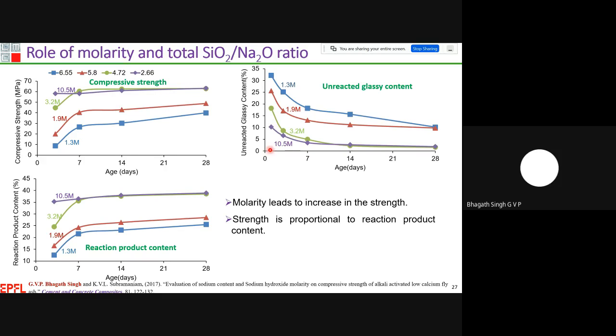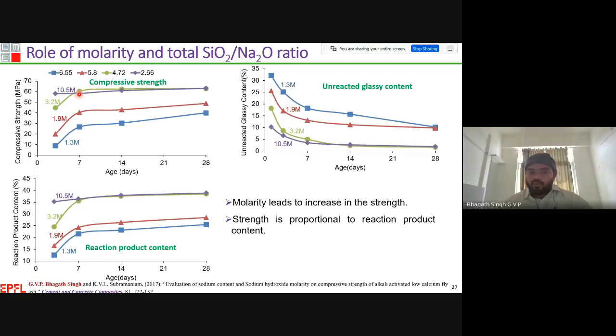Due to this reason, after 7 days, you can see the compressive strength is more or less the same. Why? Because the glass is already dissolved by 7 days, and both the 10.5 and 3.2 molars show similar glassy content and also similar reaction product. That is the reason both mixes show similar strength from 7 days to 28 days. And the compressive strength is directly proportional to the reaction product, and inversely proportional to the unreacted glassy content present in the fly ash.